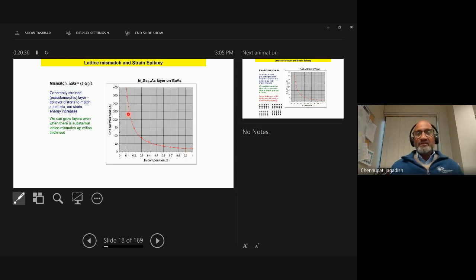So here is a case of indium gallium arsenide, which has a lattice mismatch with respect to gallium arsenide. This slide plots the critical layer thickness. The amount of layer thickness which doesn't dislocate or relax back to its original lattice constant is very much dependent on the indium composition, because the higher the indium composition, the higher the strain you're introducing. As you can see, with higher strain or higher indium concentration, the thickness of the layer becomes very, very small. So you really cannot make very thick layers. I'm plotting here also in angstroms, so you're talking about a few nanometers, beyond which it starts dislocating. So as long as you make those layers below the critical layer thickness, you'll be able to make these strained layers.